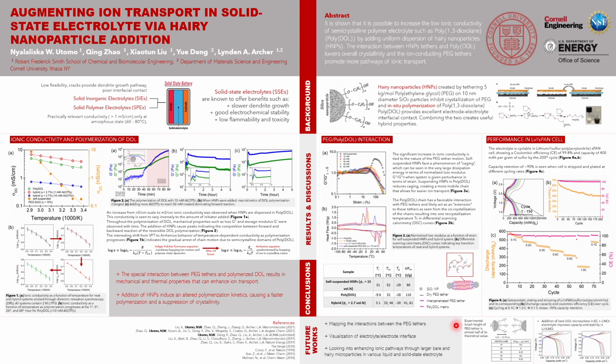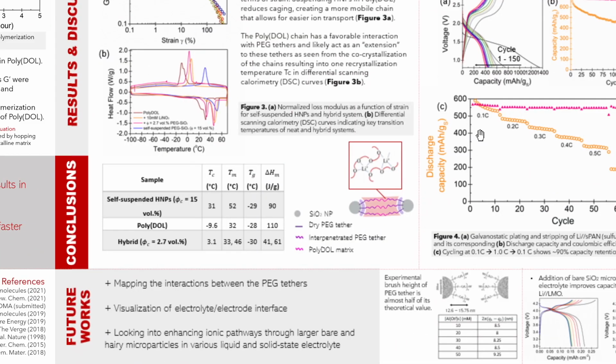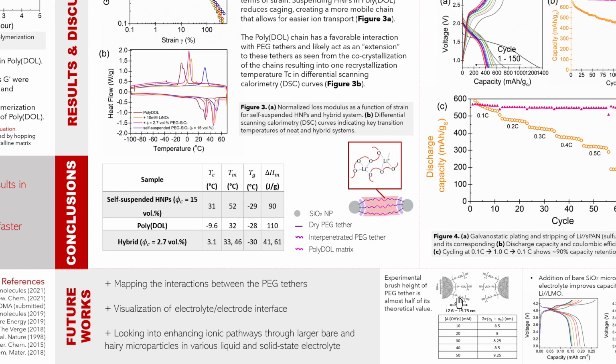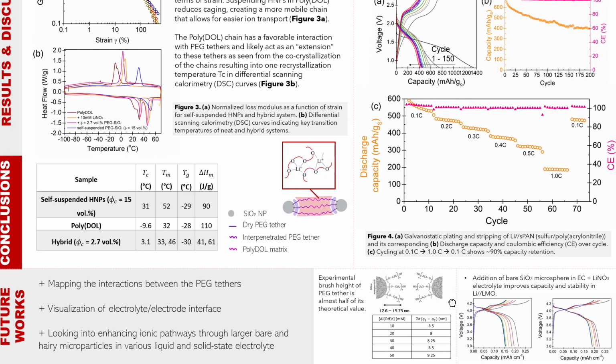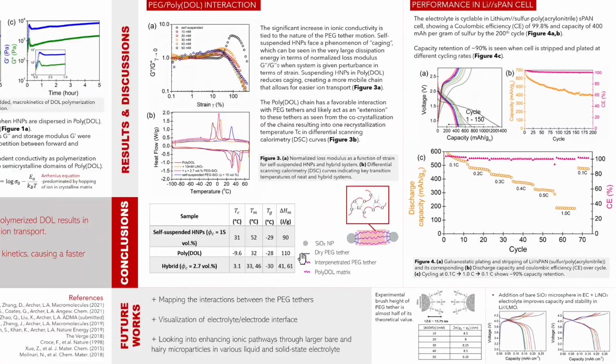In the future, I would like to dig deeper into the interaction between PEG tethers. Our small angle X-ray scattering shows that there is almost 50% difference between theoretical and experimental brush height of these tethers, likely owing to their interaction with each other. I would also like to work with different sizes of bare and hairy silica particles in different matrices.